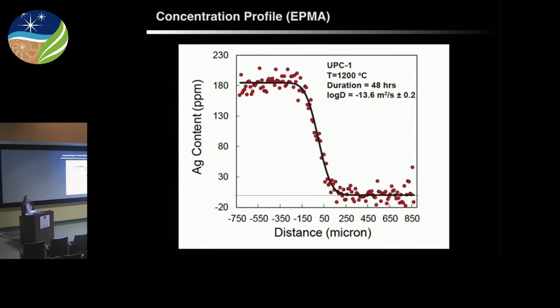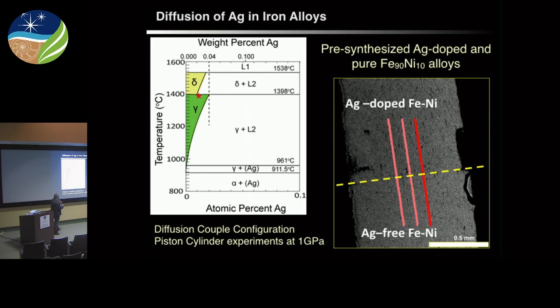Yeah, well, okay, so there's two things. So here we go. This is all taenite, right? And in kamacite, it's really not. Taenite is gamma. And this is the solubility. But all of this diffusion and closure happens pretty much above the estimated nucleation temperature of the kamacite. So even though the nominal phase boundary is within the lower end of what we're talking about with our diffusion, according to Yang and Goldstein and others, it was undercooled significantly before the kamacite nucleated. So the system had closed before that happened. Does that help?